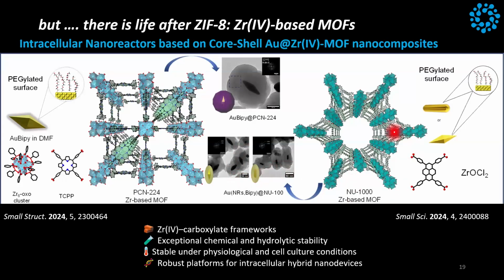For instance, with this pyrene-based MOF, NU1000, which is a very famous one. Last year, we published a couple of papers on this, and I will briefly tell you what we did. What is very cool about this MOF is that it is very, very stable. Zirconium-based MOFs sustain very acidic conditions and high temperature. There are thousands of different MOFs based on zirconium-4.